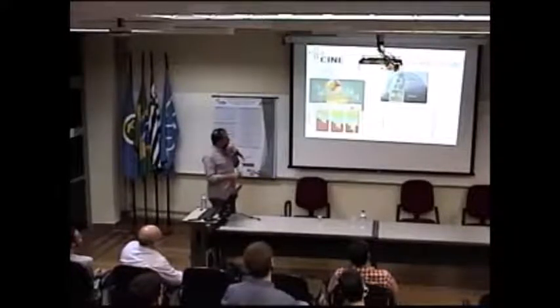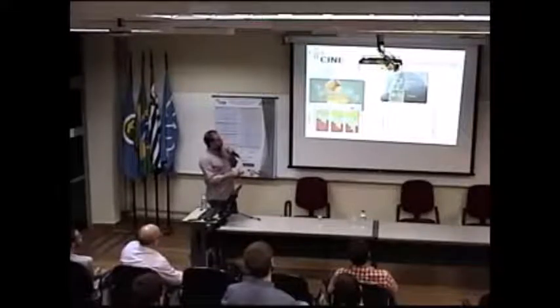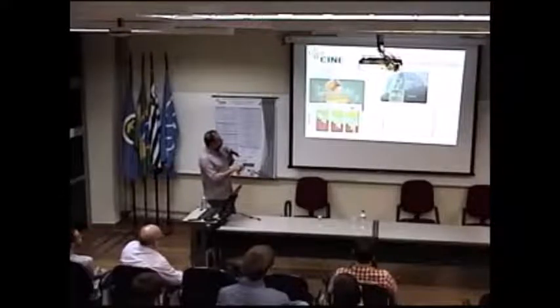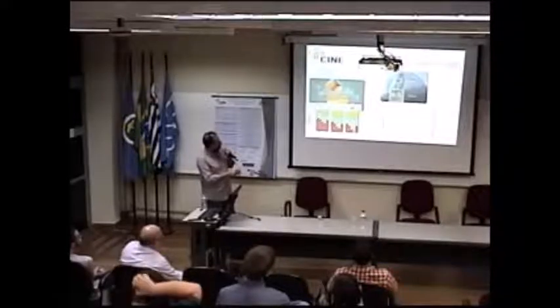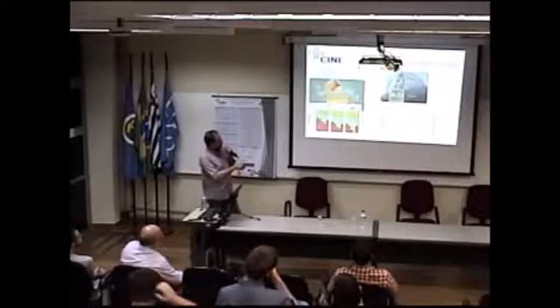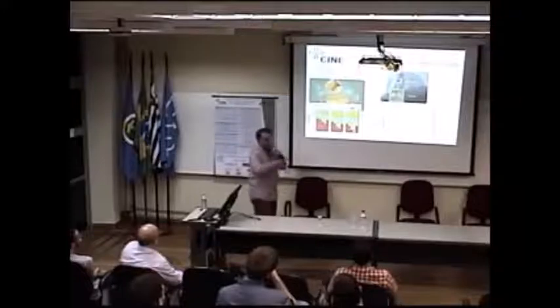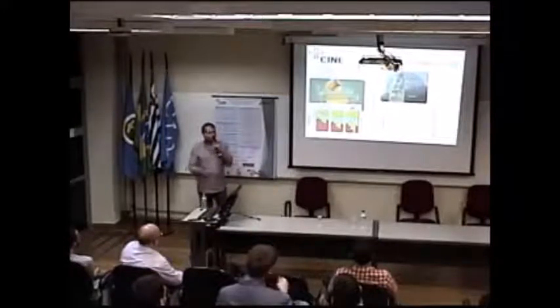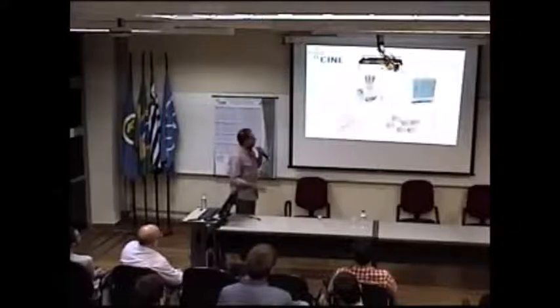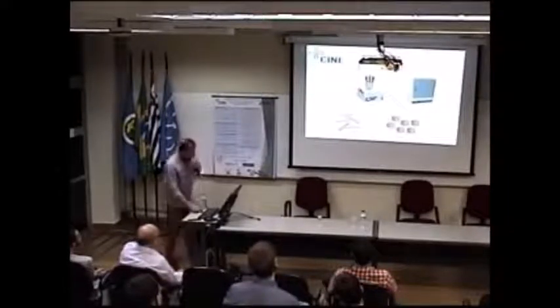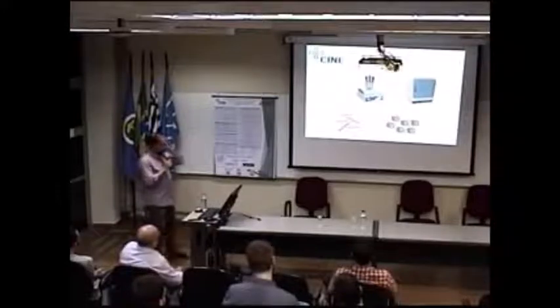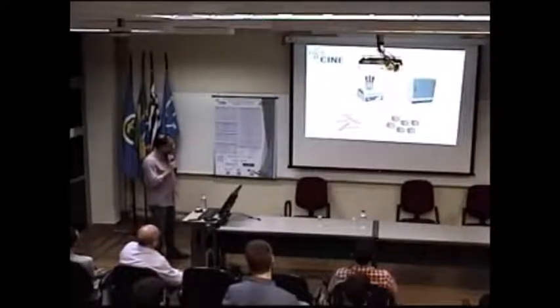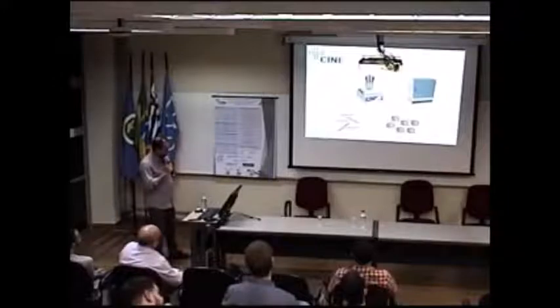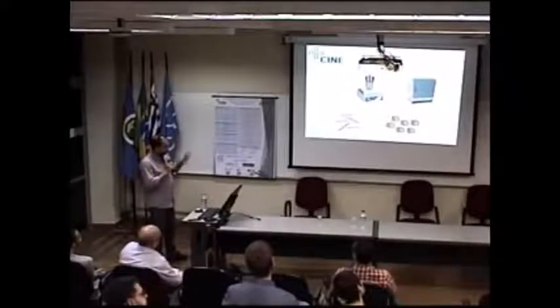Just showing you, what they do, basically, is investigate different stoichiometries of iron here, and they find the optimal one, and they operate those reactors at different potentials, and that's exactly what they have. They have the gas analysis, so they know how much ethane, ethylene, everything they're producing. And this is pretty much what we propose to do. What we've been doing at this point, we cannot do all those measurements because we don't have our experimental setup all done at this point. We are doing a lot of synthesis, trying to prepare the components of those cells.